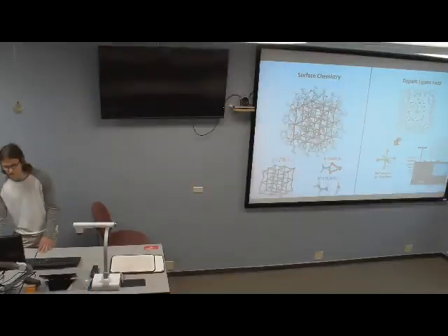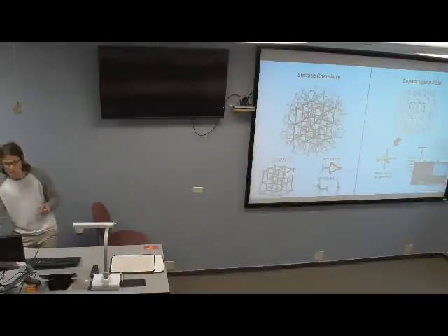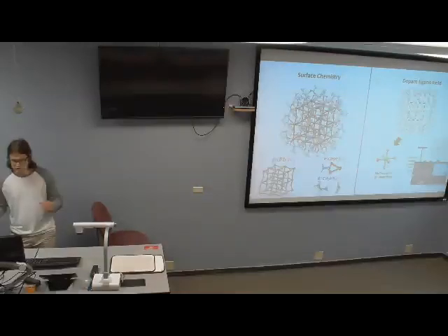So you have a deprotonated acid group here, which binds to all the surface leads, and then the proton that's deprotonated gives it to an amine, which makes it an ammonium, and then that coordinates the surface bromine. So in this case, it's mostly coulombically stabilized.